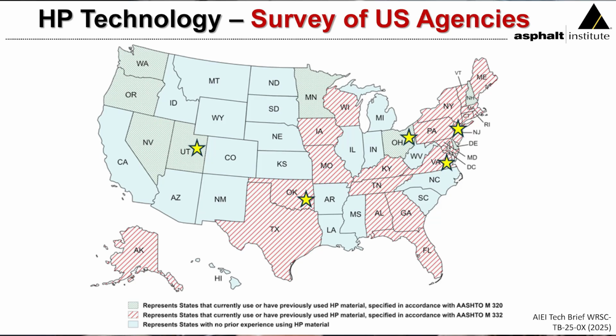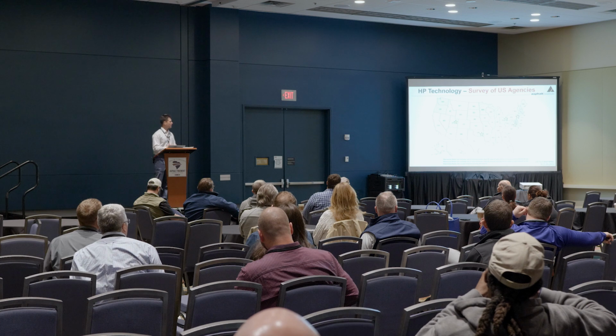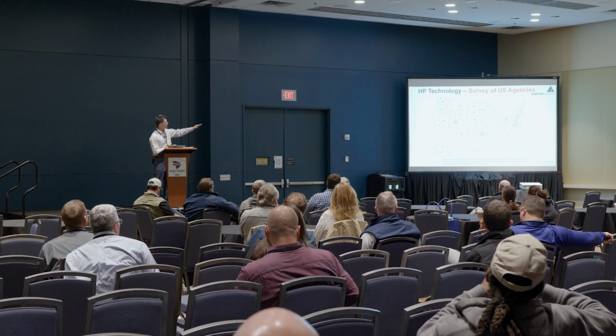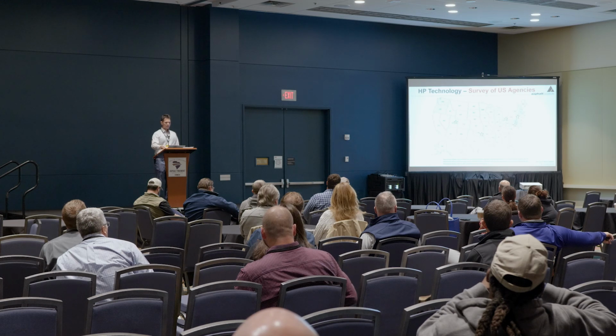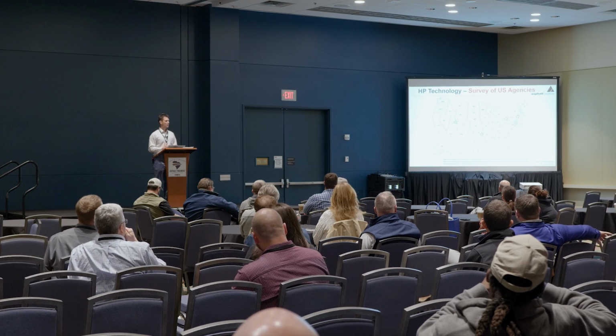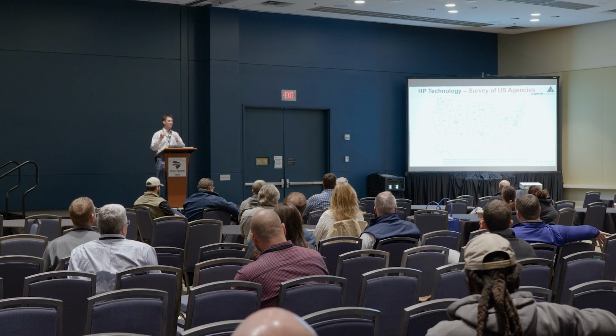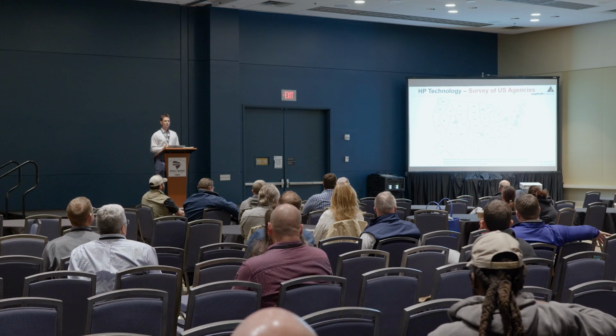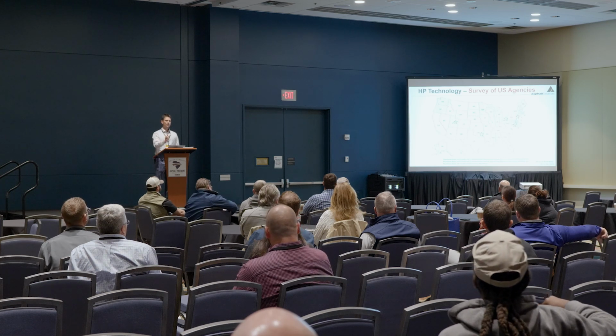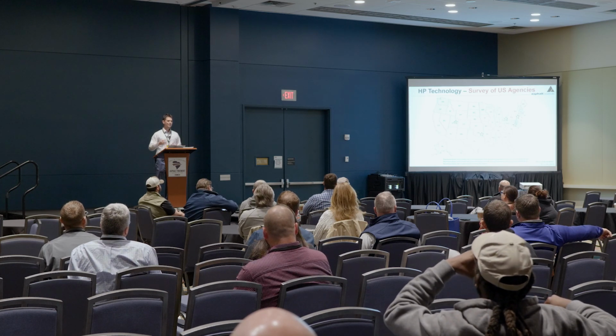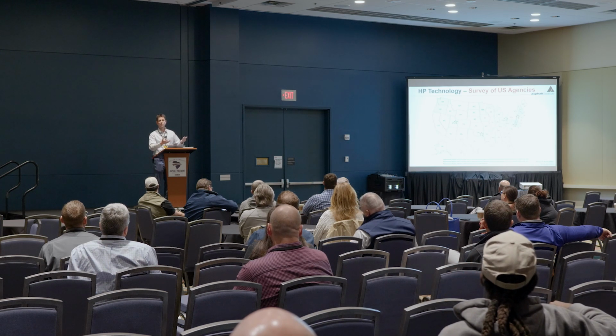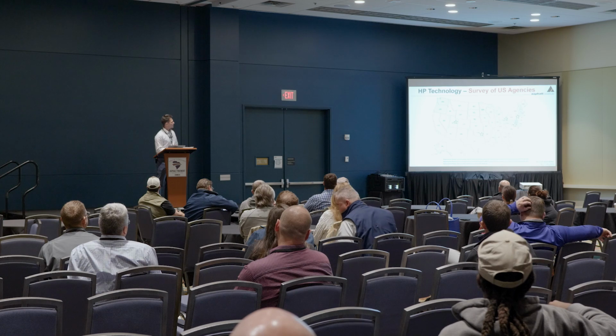Here's a map that I'm sure none of you have ever seen because this hasn't been published yet. I was given permission to show this map. This will be published in a couple of weeks through an FHWA tech brief. But what this map shows is the different agencies that have adopted this technology and developed a specification for this technology. And it's broken into the green color that you see and the red stripes. And that's just looking at the type of specification that they've used, whether AASHTO M320, which is that basic PG grade that relies on grade bumping, or the AASHTO M332, which instead of grade bumping, maintains the true grade and adds a letter such as E to say that it's appropriate for the environment, but also can handle an extreme traffic level. Okay, so it just differentiates it based on the specification.